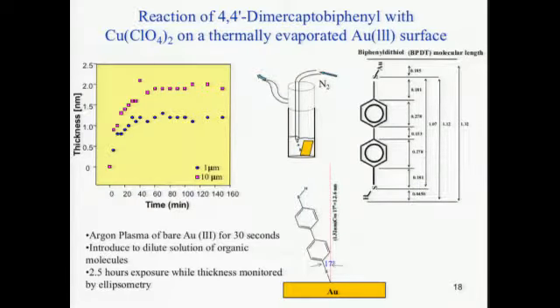One of the things you have to look at, like with ellipsometry, is you have to have an idea of what your thickness is going to be, taking into account the angle you expected to make on the surface, whether this is surface normal, and think about how much time and what concentration you need in order to make a monolayer. One of the reasons that's important is because this is two thiols. There's a thiol here, what we call the free thiol, and a thiol here that would be bonded to the gold. But they can also bind to each other to make a disulfide bond.